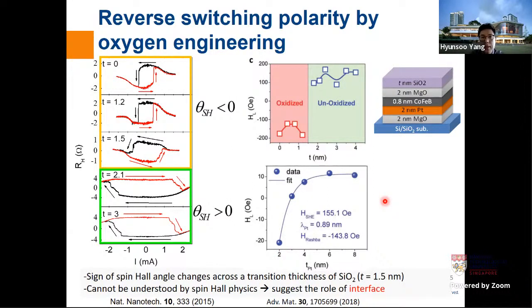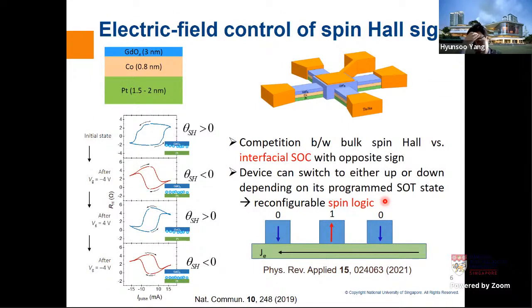So then later on, we continued this approach, and we put a gate on top of the device. And then we also put gadolinium oxide, because gadolinium oxide is known as an oxygen reservoir, so it can contain lots of oxygen. Depending on the gate voltage, you can push oxygen from the gate oxide, gadolinium oxide, into the cobalt layer, for example. And if you apply a positive voltage, you can suck the oxygen from cobalt back into the gadolinium oxide. So from the initial state, we can apply negative 4 volts, then we will push this oxygen into the cobalt. So then we can have an effectively negative spin Hall angle. Then if we apply a positive gate bias, we can bring it back to positive spin Hall angle like behavior. So we can basically switch back and forth.